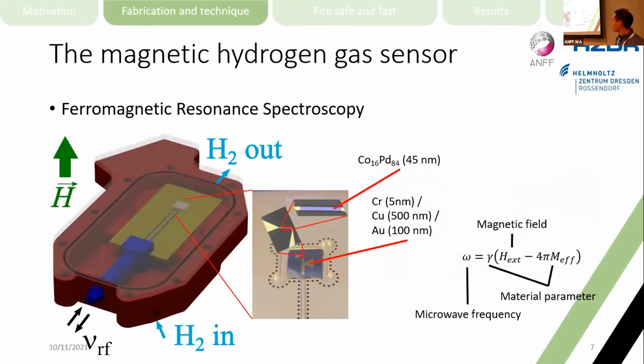Now we come back to the hydrogen gas sensor. How do we probe the magnetic properties of this cobalt palladium strip? We use a technique called ferromagnetic resonance spectroscopy. And very, very simplified, at ferromagnetic resonance, a magnetized ferromagnet, so the cobalt palladium alloy, will absorb microwave energy at a specific microwave frequency. And that microwave frequency is given here on the right-hand side.